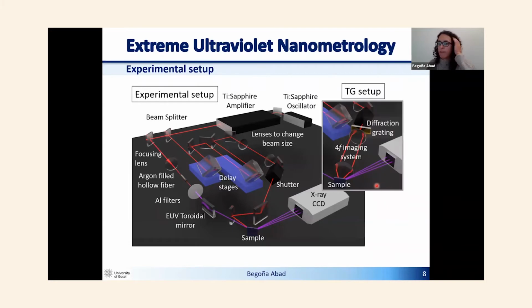There is a slightly modified version of this setup where instead of using the nanograting on top of the sample, we just create an interference pattern with two beams on our sample. That interference pattern gives rise to a sinusoidal temperature profile, and we also probe the diffraction of that interference.